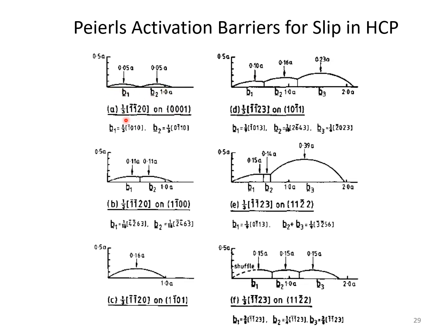And I showed in the video how you can't do that for this configuration on the basal plane, because if you move one layer and then you try to move the next consecutive layer above it, there's a barrier to the movement. There's no easy route through in the same direction. Kind of difficult to conceptualize, but that's where the ball models help.